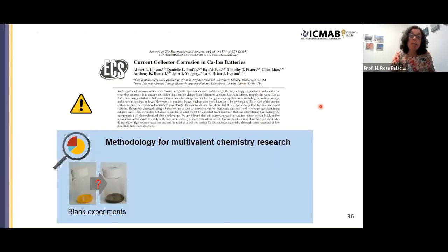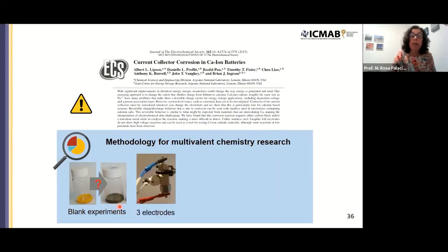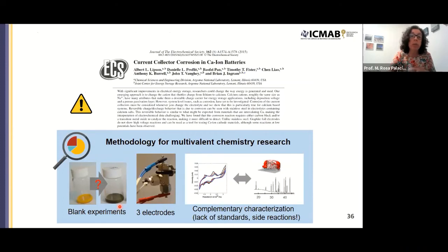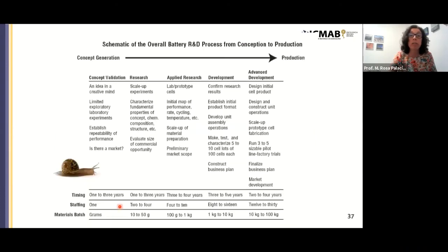So finally, the strong message is that for multivalent batteries, you need to do a very careful definition of research protocols with blank experiments. This is simply aging of V2O5 in one of the electrolytes we use, and you see that it is reacting even in absence of current. Work with 3 electrode cells to have a reliable reference electrode and use complementary characterization techniques.